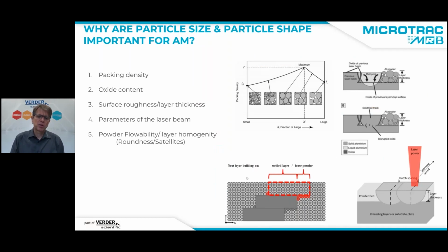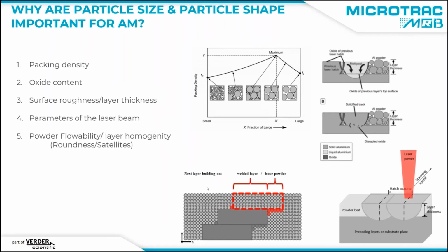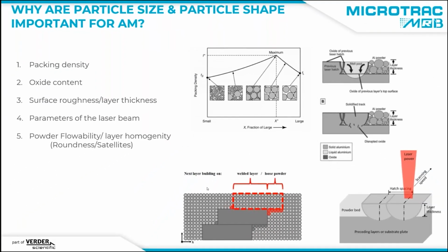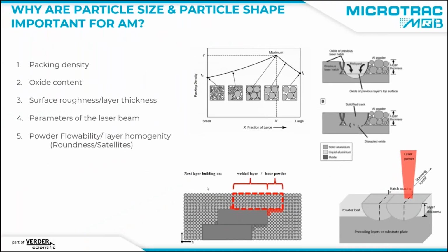So why is particle size and particle shape analysis important for additive manufacturing? First of all, it's about the packing density. When we have powder with a nicely wide size distribution, all the gaps between the bigger particles can be filled by small particles and we achieve a good packing density. If we have only small particles or only big particles, this cannot be achieved. Also, the oxide content, that means how much surface area the particles have and how much contamination is on the surface, depends on the particle size distribution of our powder.